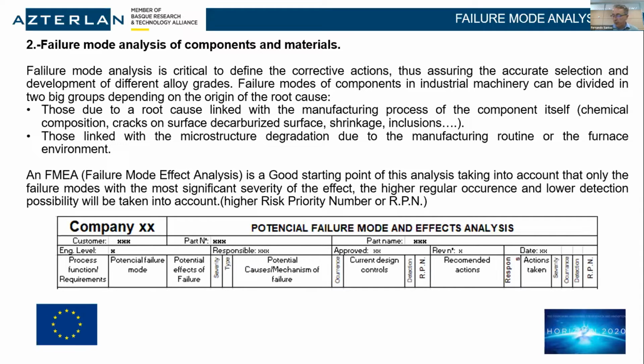Let's put another example of a bad analysis of the failure mode. For example, if we identify a problem as creep, and it's not creep, it's thermal fatigue, the final solutions that we will give in terms of chemical composition variation are going to be very different in one case or the other. And what is more severe, we can take one decision related to chemical composition that is going to adversely affect the final performance of the part. So as I have said, it's very important to define very well the failure mode and also the root cause. We will go further on this in next slides.